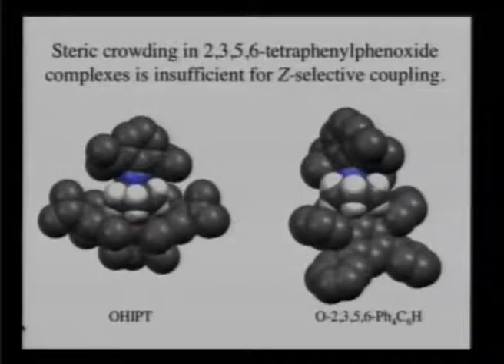The 2,3,5,6-tetraphenyl phenoxide doesn't work at all. We have crystal structures of both these metallocycles. This one I've shown you with the big HIPT ligand and the 3 protons pointing down, touching the isopropyl protons, which aren't shown in this case. In the case of the tetraphenyl phenoxide, you would think that's a big ligand, big enough, but it's not big enough in the right way. There's a big hole right here in the middle of this metallocycle so that an R group can point down, and this does not work at all for selective couplings of terminal olefins.